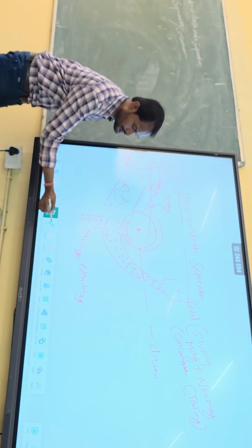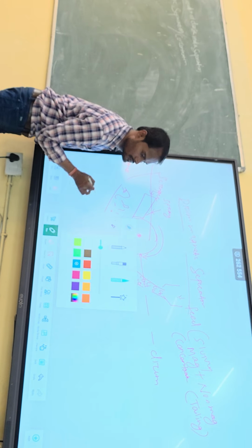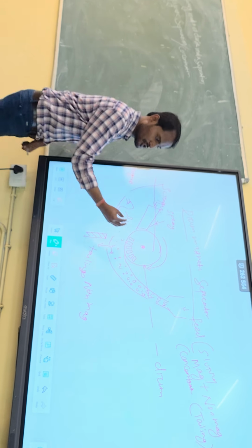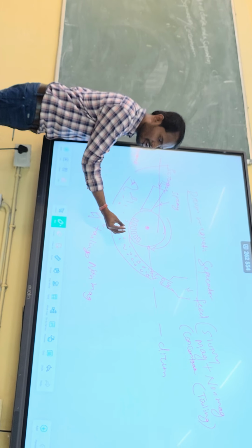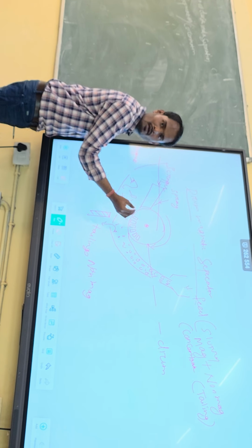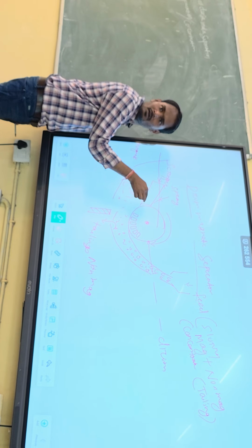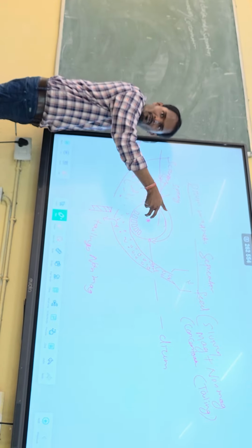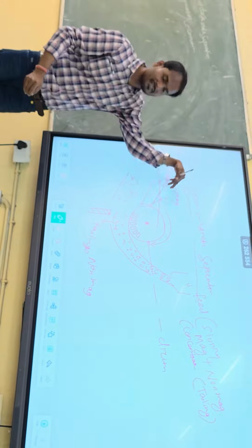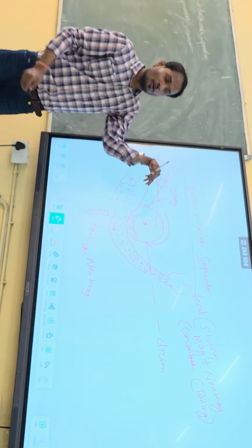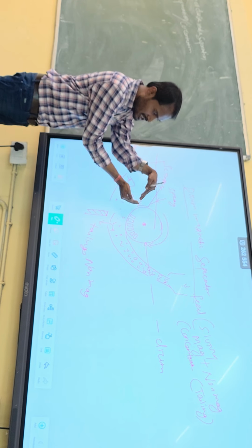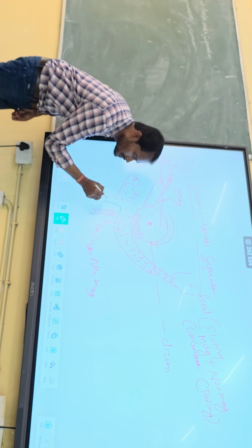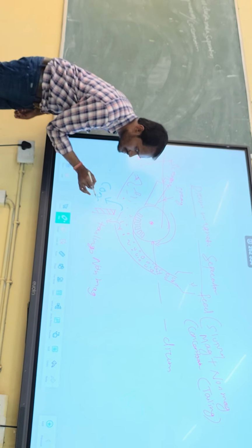You understand my point? And those magnetic minerals will stick to the drum. Okay? So we have put a scraper here. That means they will attach to the drum and move with the drum also. So there is a scraper and there is a sprayer, where you are spraying water. So they will come and touch this one, and they will fall down. So you will get concentrate here.